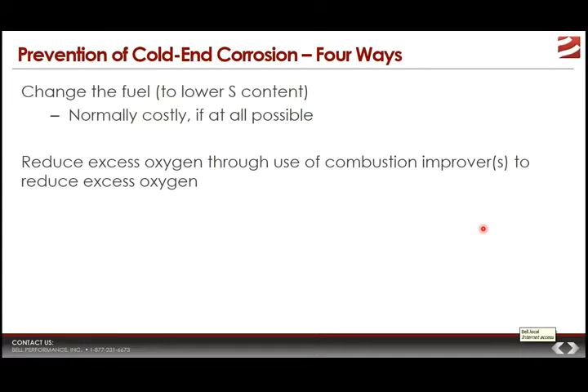Second thing, they could try to influence the amount of SO2 and SO3 formed by the amount of oxygen that they supply. Because these sulfur gases are formed from combining the sulfur in the fuel with the oxygen in the air, if you can reduce excess oxygen, the amount of oxygen that's available, you can reduce SOx formation. However, the downside is you cannot reduce it too much, because you need a certain amount of oxygen in order to maintain your optimal combustion level and your optimal efficiency level.